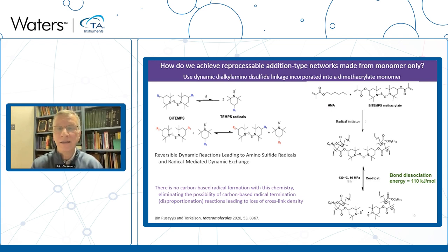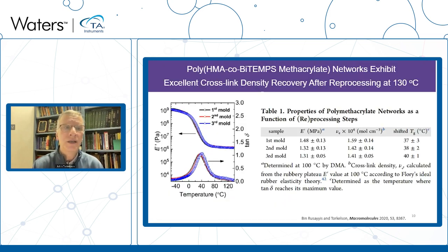The dialkyl amino disulfide bonds come apart, leaving a branched system. We can reprocess that, and then upon cooling, it returns to the network in this particular case. This material here we show, again, looking at modulus as a function of temperature. In the rubbery plateau region, we end up with excellent reproduction of the modulus as a function of remolding. In these cases, again, showing that we get excellent recovery of cross-link density in these systems as a function of